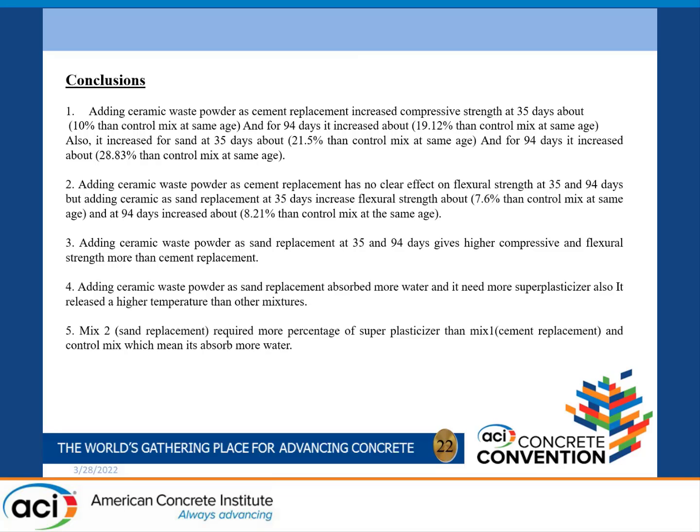Adding ceramic waste powder as sand replacement absorbs more water and needs more super plasticizer. Also, it released a higher temperature than the other mixtures. Last, mix 2, sand replacement, required a higher percentage of super plasticizer than mix 1, cement replacement, and the control mix, which means it absorbed more water.